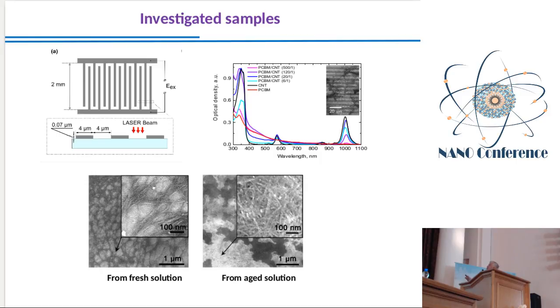Here is the photoconductivity of CNT PCBM films. In fact, if we prepare just PCBM films, or just carbon nanotube films, they have very low photoconductivity. Here it's not zero, but it's almost zero. But with adding of PCBM, conductivity increases. After reaching some PCBM ratio, conductivity starts to drop again, and this is because PCBM is a non-conductive material, and when we have a high concentration of PCBM, these carbon nanotubes become completely separated from one another, and current cannot pass through this carbon nanotube network.